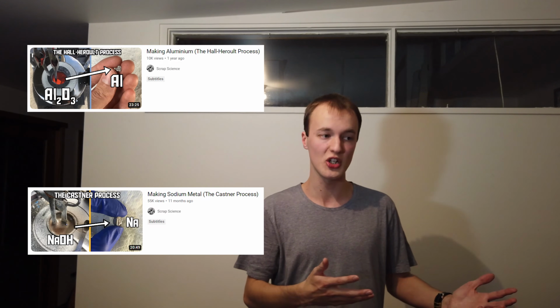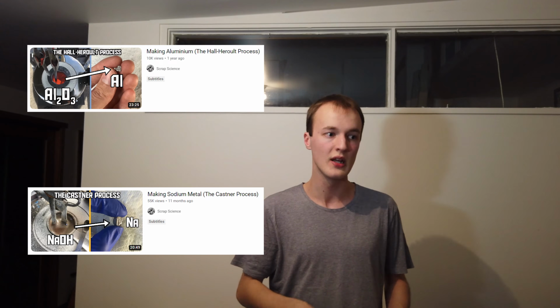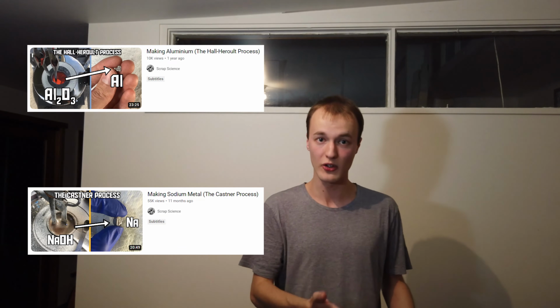So we started out with aluminium and sodium generation by the electrolysis of molten aluminium oxide and sodium hydroxide, both of which weren't too difficult with the right setup. We then moved on to generating lithium metal from lithium chloride. This was a little bit more challenging because of the generation of chlorine gas and the fact that the yield was heavily dependent on the type of electrode that we used as the cathode. We then tried making boron by the electrolysis of molten borax. That didn't work, so we're not going to count that.